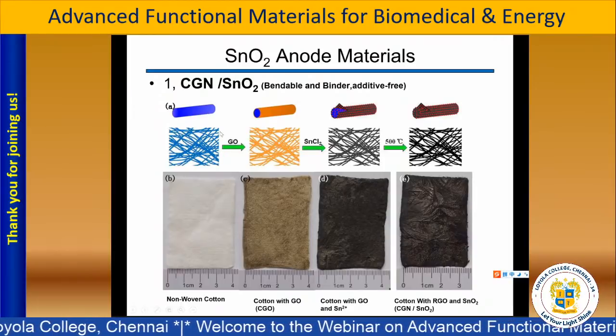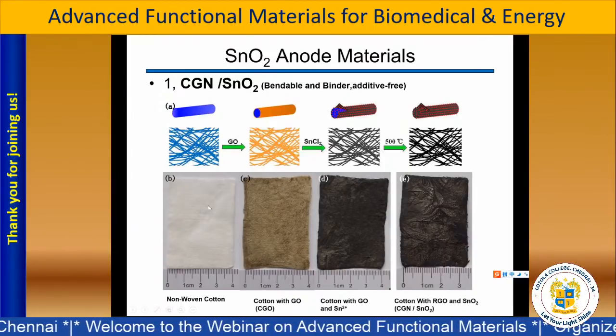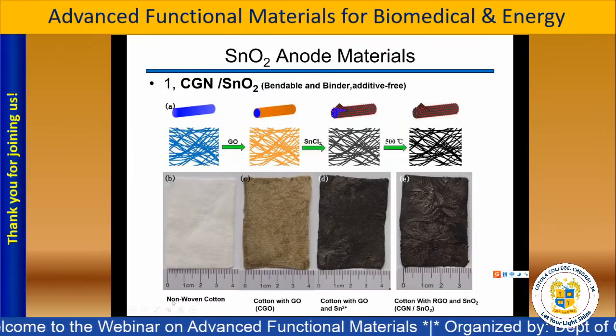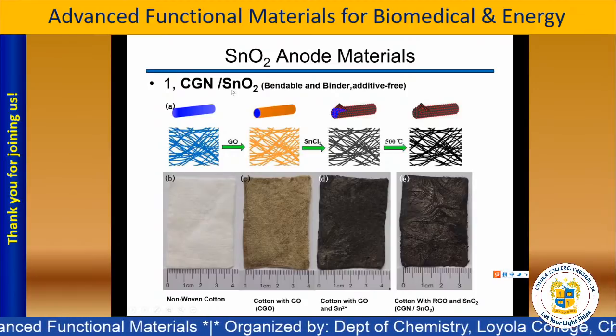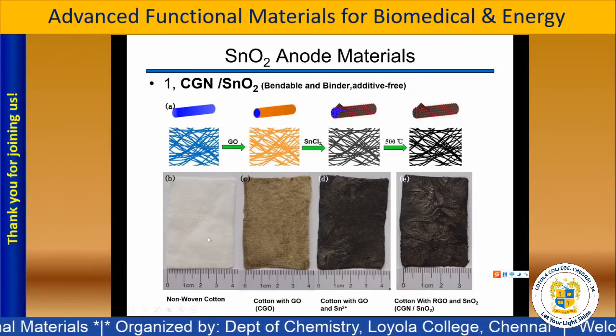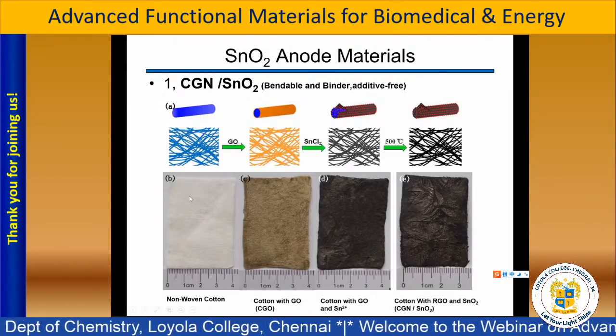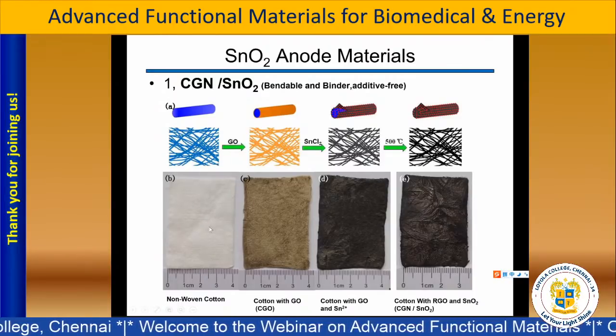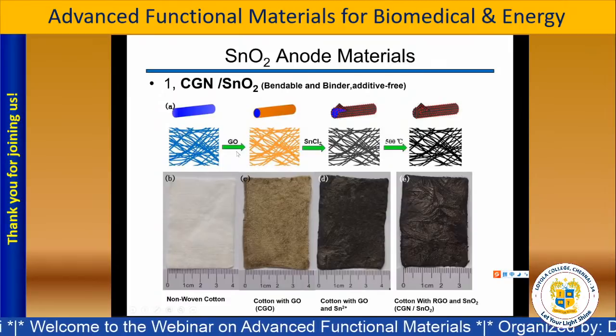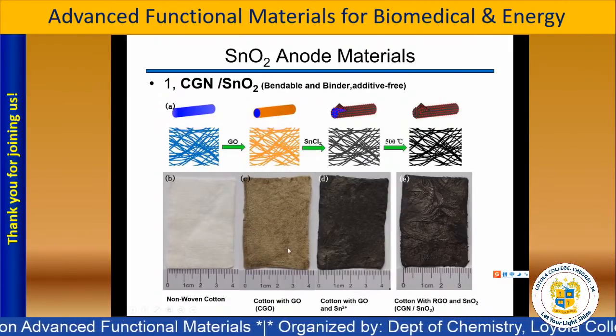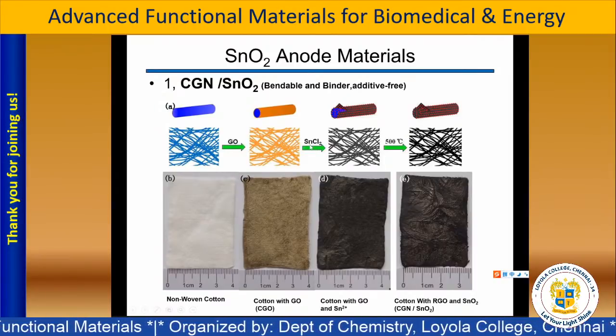Let me interpret the meaning of this material. We use the raw material, non-woven cotton, because this anode material copies the cotton's structure. So this material should be flexible or bendable. We soaked this cotton into a gel solution. GO means graphene oxide. We soaked it in the gel solution, and we added the tin ion into this material,